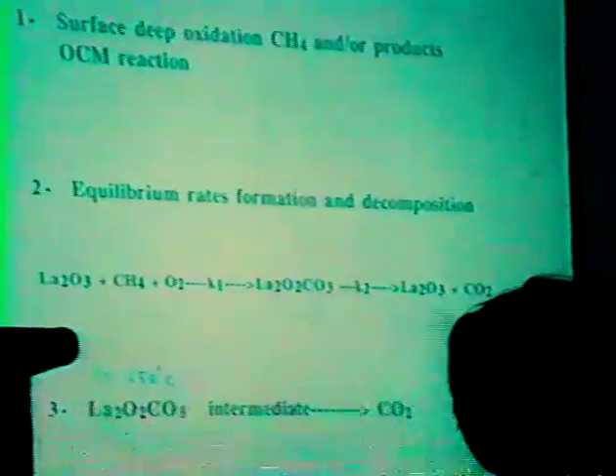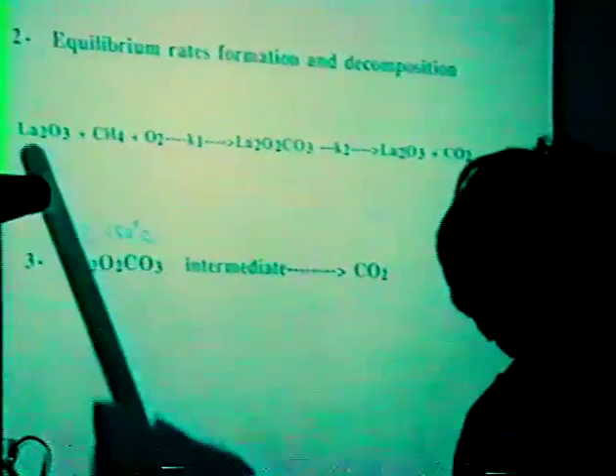So, as this oxycarbonate cannot proceed from the gas phase, we think that it is produced by the deep oxidation of methane, ethane, or ethylene on the surface of the catalyst. In addition, the fact that the amount of oxycarbonate produced is constant during the reaction suggests an equilibrium between the rate of its formation via deep oxidation on the surface of the catalyst and its rate of decomposition. So, at this intermediate temperature, in our conditions, we think that the oxycarbonate acts as an intermediate to produce the CO2.